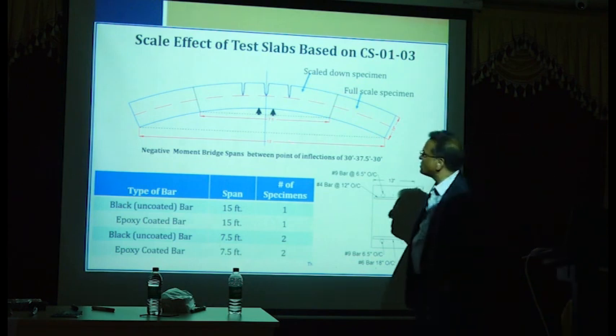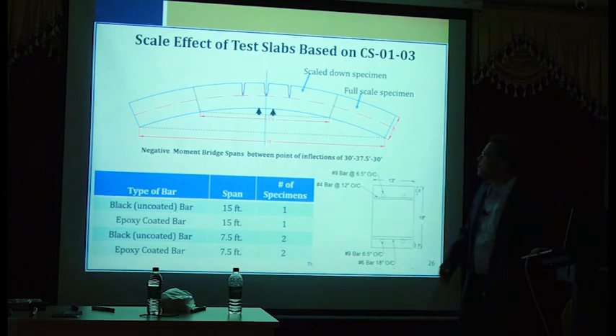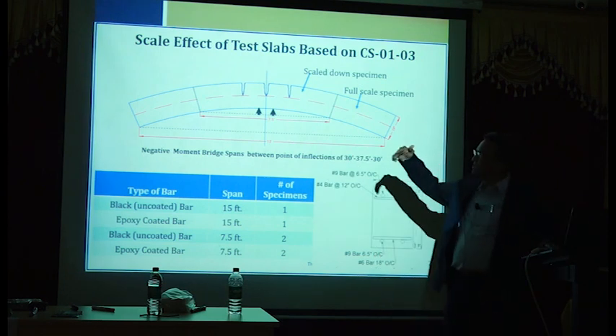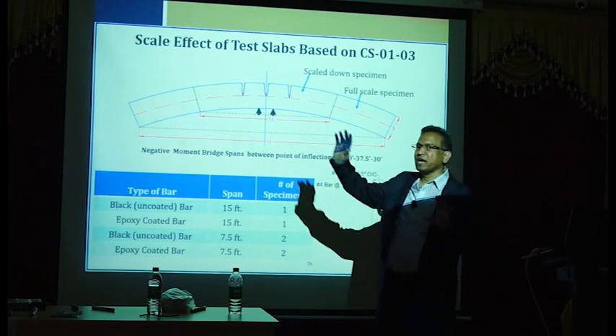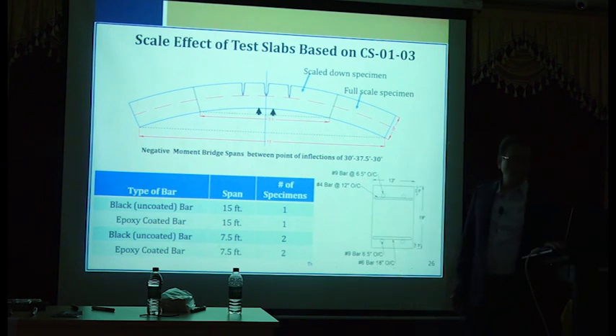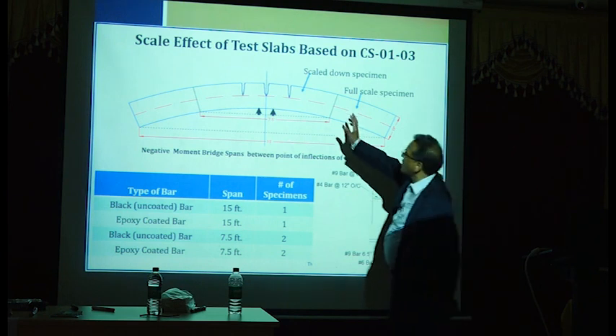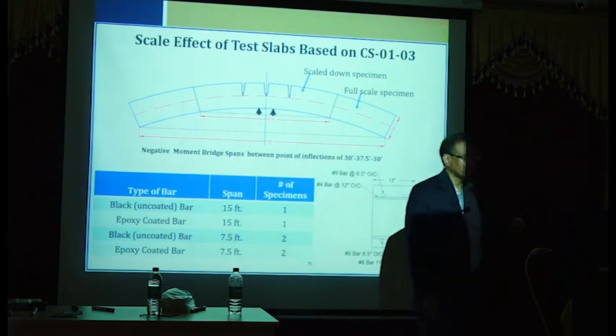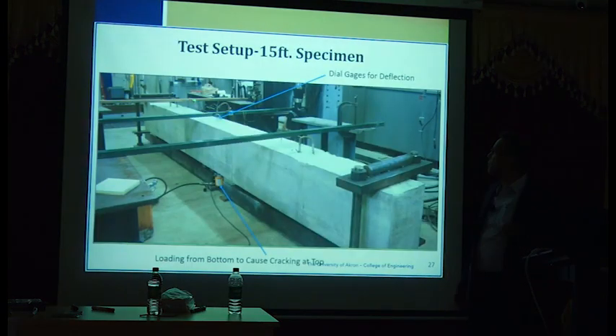So initially we were not sure, so Shrikant did some very long beam tests, 15 feet to start with, and then he did 30 feet tests also. He correlated between the scale tests and full-scale tests, and then we found some correlation, and then we also got our crack width predictions from the actual theoretical work, and then we did very long beam tests. This is probably about 24, 30 feet. 30 feet is like how much? About 10 meters. Slightly less than 10 meters, but about 10 meters. Yeah, a little bit less, but it's a very, very big test actually.